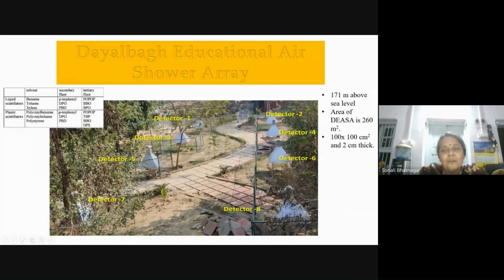And they have been put in a particular order because this is called a mini array, where the distance between the detectors and the detector configuration and how it is put on the ground is very important. And as you can see in this slide, the material is polystyrene, which was the solvent, and in that we had put para-terphenyl, and POPOP was another tertiary fluor which we had added. This POPOP is for shifting the wavelength to the region which gives you the maximum sensitivity for the PMT, because these detectors are basically detecting very small quantum particles from the air.